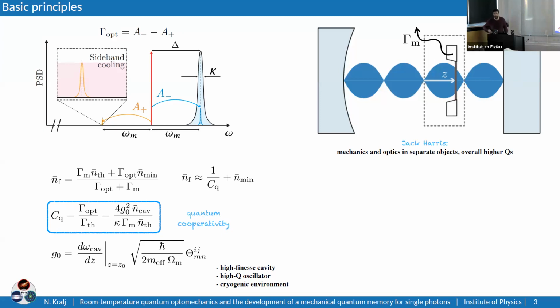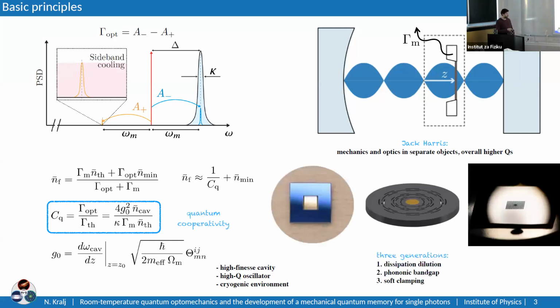Why silicon nitride? Well, that's a twofold answer I could give you. First, from the optical side, because at 1064, and if you want to do some other stuff with telecom, as I'll show you later, the reflectivity of silicon nitride at these wavelengths is non-zero, but not too high. Why do I not want to make it too high? Because if that approaches unity, then effectively I'm going back to having a mirror as the mechanical resonator, and in a sense, then I don't really require one of these two mirrors anymore. And so I'm basically going back, which is not what I want. So the reflectivity, depending on the thickness, is something like 20%.